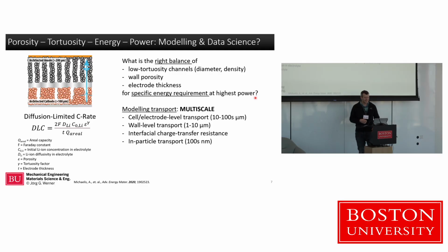Now, this looks like something that should be cool to model, especially our straight channels, pretty straightforward. But I do want to emphasize the multi-scale aspect of this problem. We have these particles that are usually a few hundreds of nanometers. The interparticle pore space is tens to hundreds of nanometers. We have these channels, let's say we put them into the micrometers, 1 to 10 to 20 micrometers or so in diameter. And then the electrode thickness is on the level of 100 micrometer plus. So we're spanning orders and orders of magnitude in scale, which for simulations can get a little tricky here and there if you're trying to resolve all the important resistances, mass transfer limitations, et cetera.